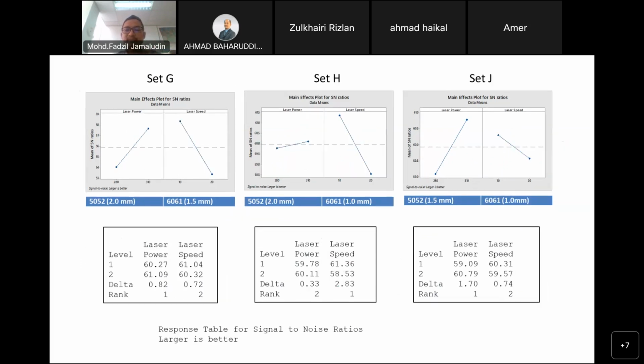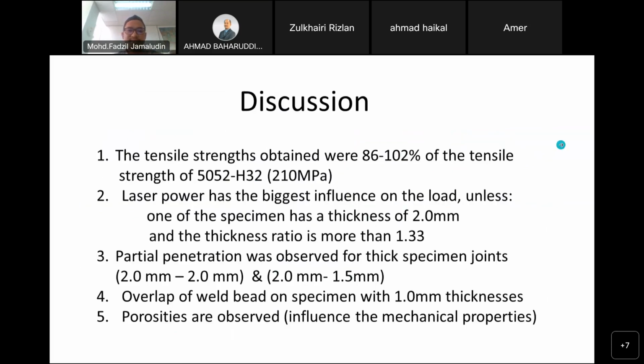Okay, this is overall for all the samples, 3 groups. For the tensile, what we have observed is that it achieves 86% and is nearing the tensile strength of the lower parent material, or lower strength parent material. The laser power was shown to have the biggest influence on the load, unless one of the specimens has a thickness of 2 mm. I think the 2 mm was because the weld was not successfully made.